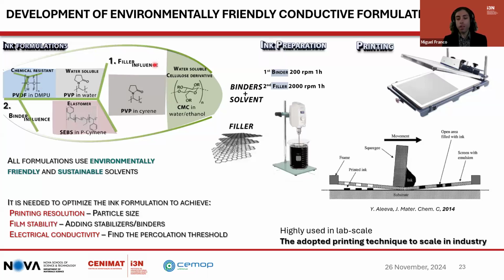It is to remind that all these solvents tend to be environmentally friendly alternatives, especially Cyrene. It is a biodegradable solvent, which is an alternative to DMF and NMP, and this solvent has a great capacity to stabilize graphene, which allows stable graphene dispersions with high concentrations.